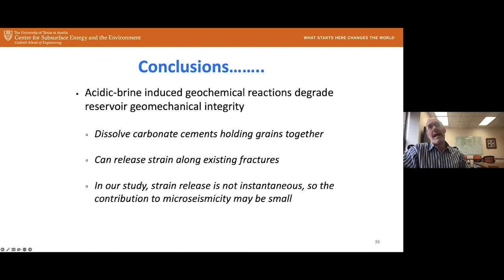Another conclusion is this acidic brine induced geochemical reactions, and that degraded the reservoir geomechanical integrity. In our system, it dissolved carbonate cements that held these grains together. It released strain along an existing fracture, but the strain release wasn't instantaneous. So it's not clear, when you have these reactions and the time scale they're occurring over, at least on the order of days, that that sort of event would contribute to this microseismicity. That's, I should say, still an open question. Our results would suggest that, at least for the Bandera sandstone, it's happening over multiple days and we wouldn't get those types of readings.